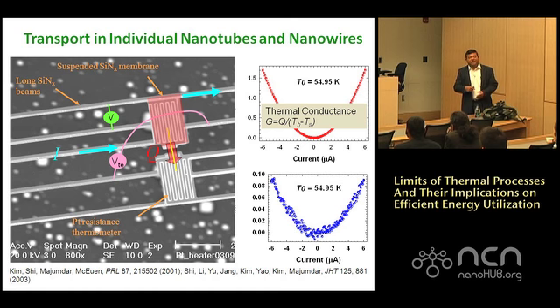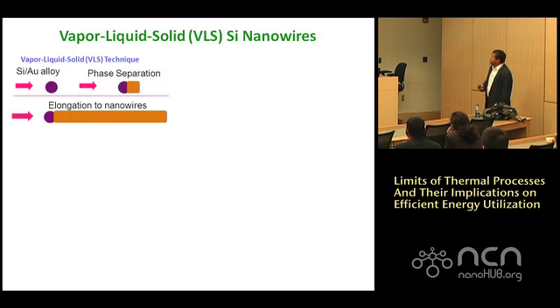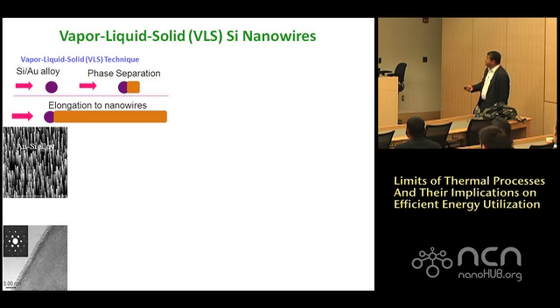And we have used this for carbon nanotubes. Whatever one-dimensional nanostructure we can find, we can put it on it and see what the thermal conductivity is. So we said, okay, let's look at these early experiments of a new way, actually not so new, there were some experiments in the 70s, but nevertheless a very interesting way of making single crystal silicon nanowires. This is single crystal, made by putting a catalyst of gold on a surface and then exposing silicon. It forms a silicon gold alloy, and beyond a certain point, silicon is precipitated out, which forms a nanowire of the size of this particle.